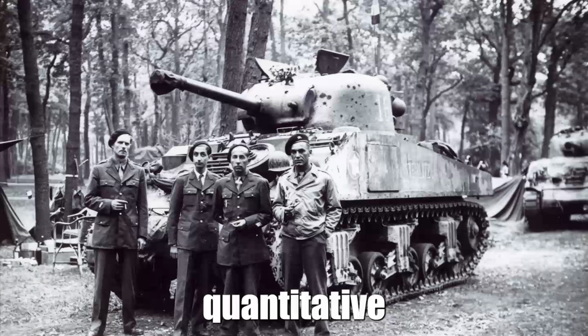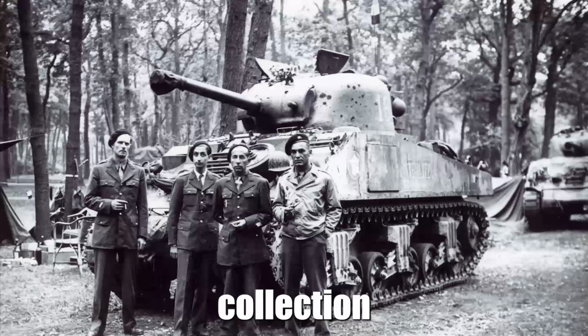Morrison ran quantitative analysis on his sample collection. Plates from early 1942 production averaged 0.63% manganese. Plates from mid-1943 averaged 0.48%. Plates from October 1943, when manganese shortages had become acute, averaged 0.41%. The correlation with combat failures was undeniable.